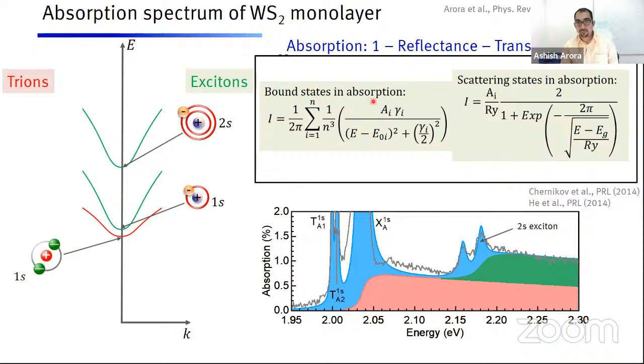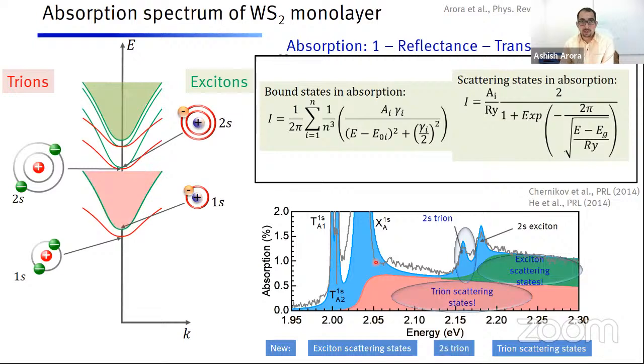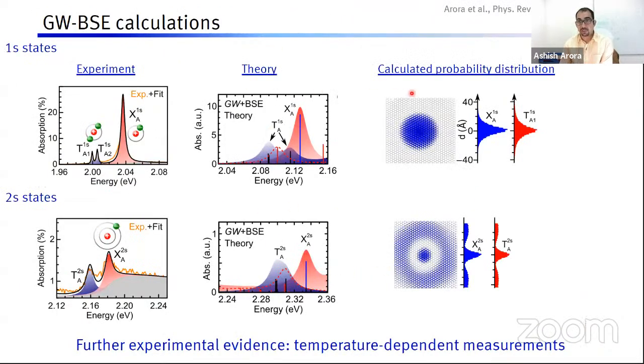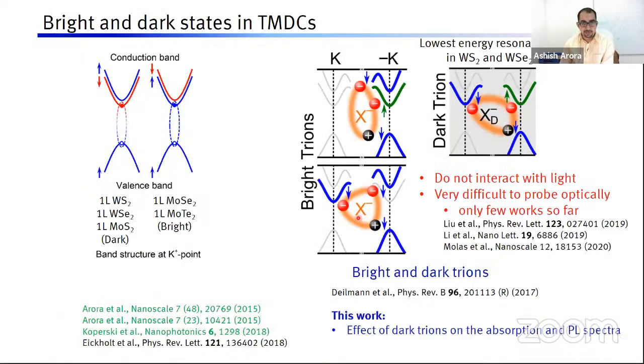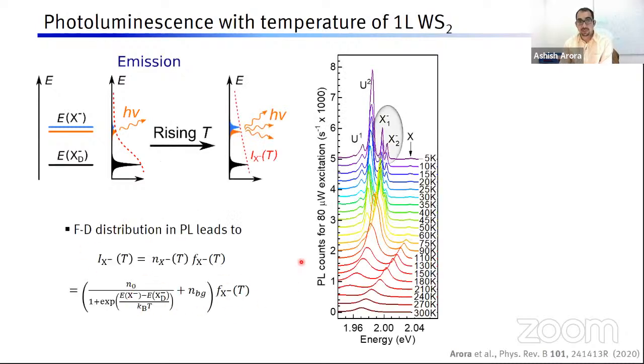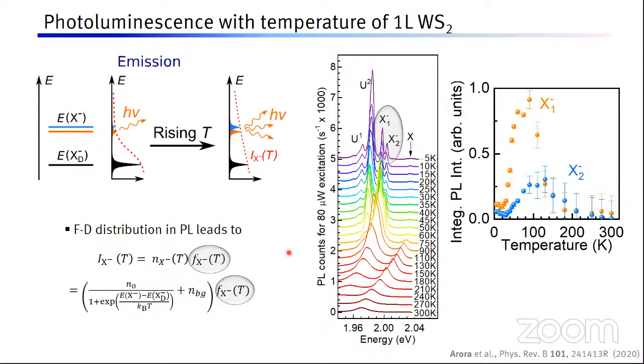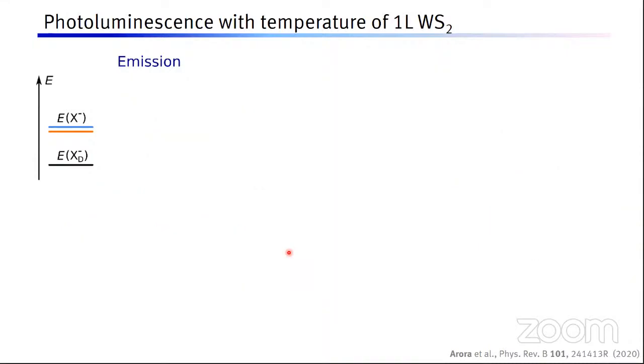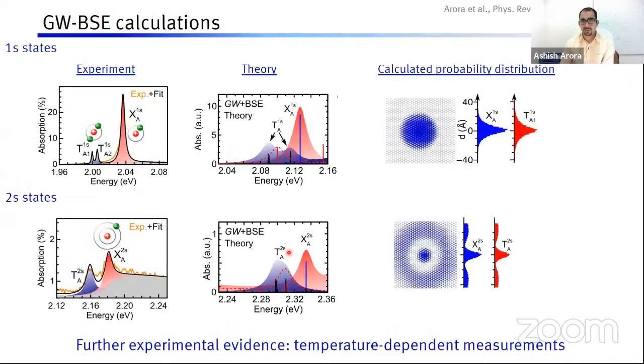So what kind of equation? We have modeled either the spectra, or there is some modeling involved here. Now this is an ab initio theory, which is done by my colleagues. And then there is another type of modeling involved in this work, which is the Fermi-Dirac equation, essentially multiplied by the oscillator strengths. Yes, sir. I was asking about that absorption spectrum, like finite-difference time-domain modeling. You mean these ones here? Yes, absorption spectra. These are done by my colleagues. I am not an expert, but what I can tell you is these are some kind of DFT, density functional theory calculations with GW corrections on top, and then you solve the Bethe-Salpeter equation for introducing the Coulomb effects to calculate the absorption spectra of excitons.